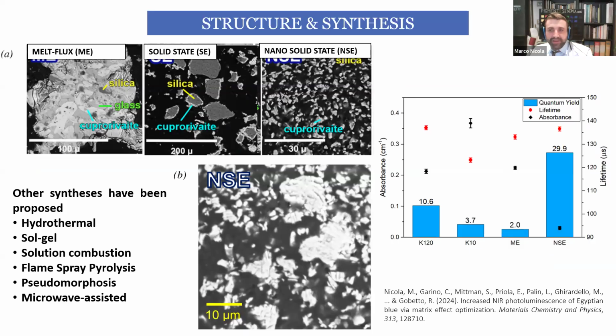In ancient times, they used a melt flux method to produce Egyptian blue. So they take sand that is basically made of silica and calcium carbonate. So probably they already knew where to find sand with the right ratio of calcium carbonate and silica. So they knew where to source this kind of sand, and then mixed in a copper-containing material and the flux, that is something that contains sodium or potassium.